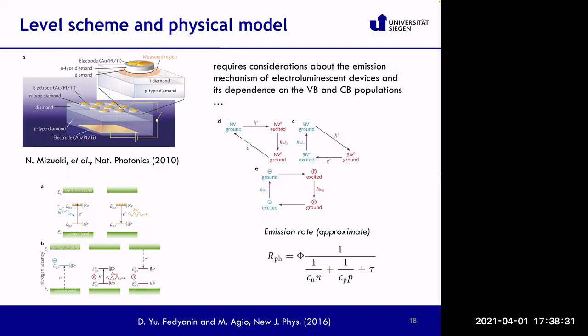The same situation can take place for the silicon vacancy. So you see the cycle in the other panel when you go from silicon ground, silicon excited, and silicon ground neutral state. The difference is that in this case, the state that emits a photon under electrical pumping is negatively charged. So therefore, the emission properties are different. And this very much depends on the energy level structure of the color center in the band gap of diamond. I don't want to go much into the details because this would be a bit complicated, but it is to tell you that the emission properties by optical pumping and by electrical pumping are very different, and they do not correspond to the same emission spectra because of this charge state that can be active or inactive under electrical pumping.